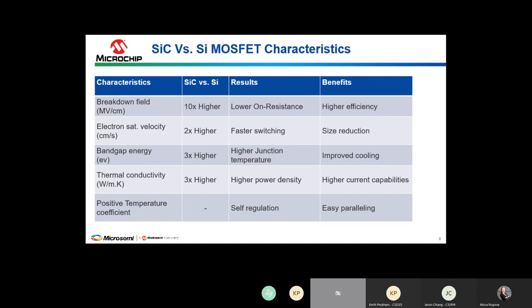Also, because of the higher energy, the breakdown electric field is much higher, and because of that we don't need as thick a silicon or epi layer, so the on-resistance is therefore much lower — all things being equal — over regular silicon. This lower on-resistance means smaller die size and higher efficiency. The thermal conductivity of silicon carbide is also much higher than regular silicon, again relating to improved cooling requirements.